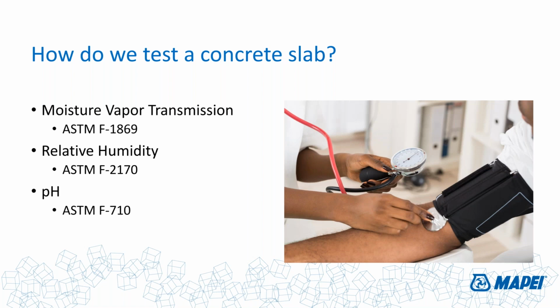there are three tests that are pretty important. The ASTM F-1869, that's the moisture vapor transmission rate test. We have a relative humidity test, which is the ASTM F-2170, and the pH test, which is included in the ASTM F-710 documents.